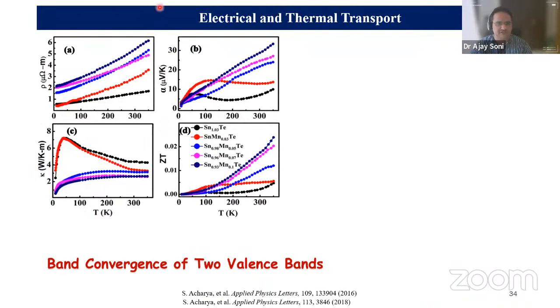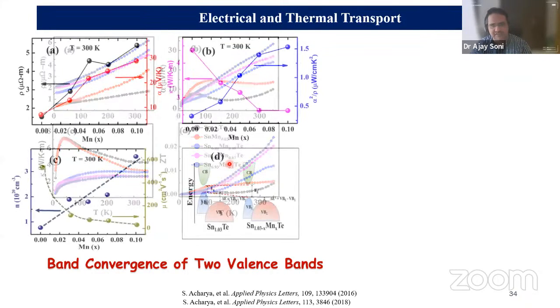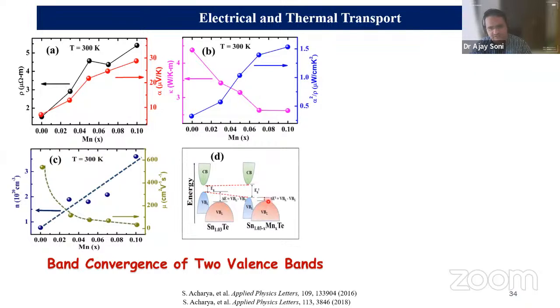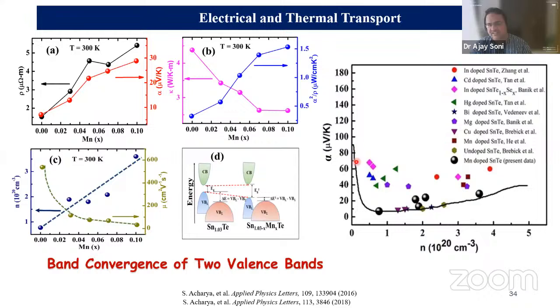Okay, so this is the data which we have seen for the Mn doped tin telluride, SnTe. This Mn doping plays a significant role, as it changes the Fermi energy in these materials, which can be reflected in the number of charge carriers as well as the mobility. And you can see that this is the Pisarenko plot of the Seebeck coefficient as a function of the charge carriers. This is the line below which the materials are not good. So the materials we have prepared have a better performance as well.